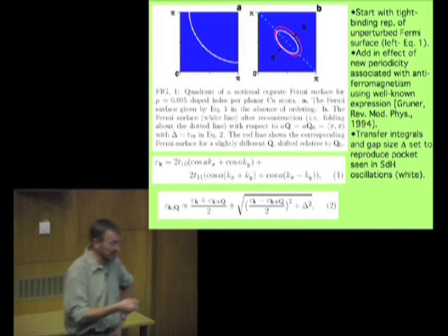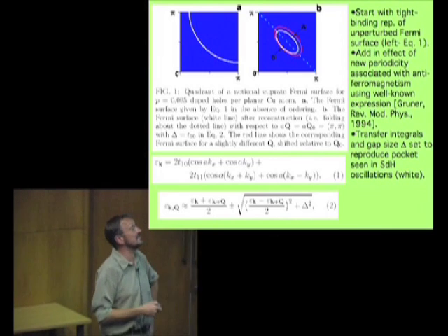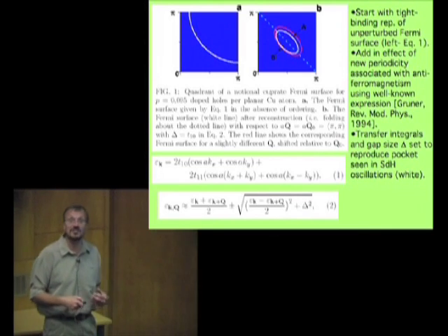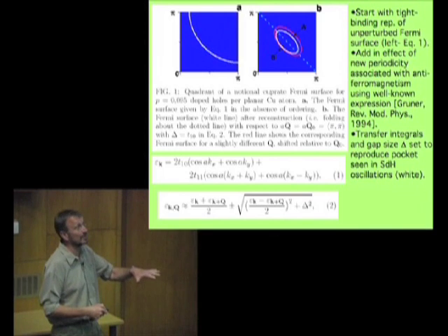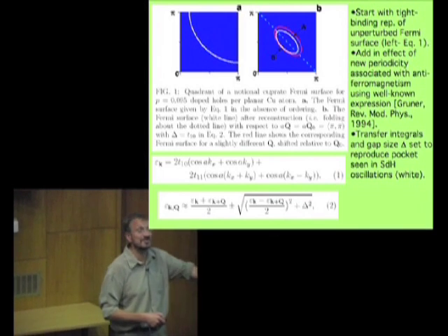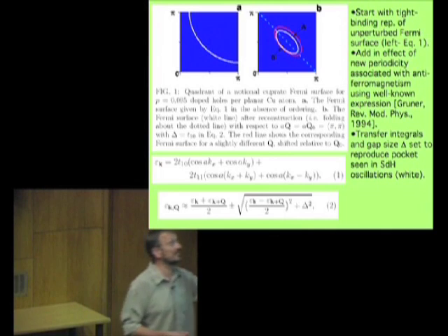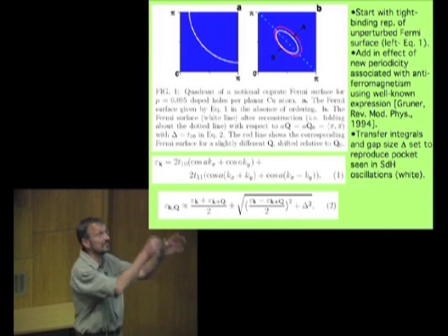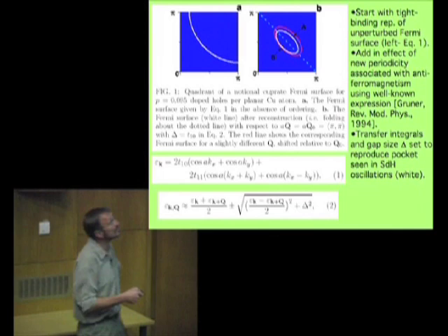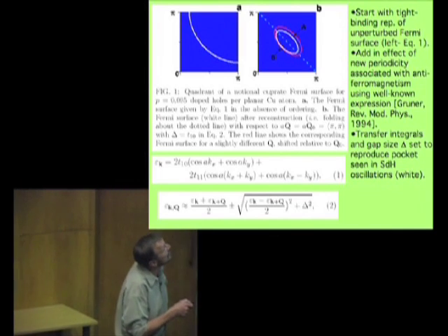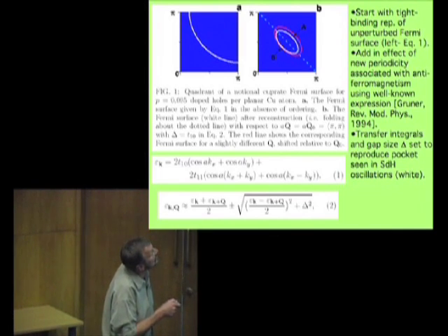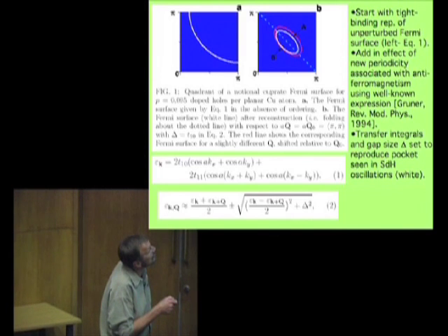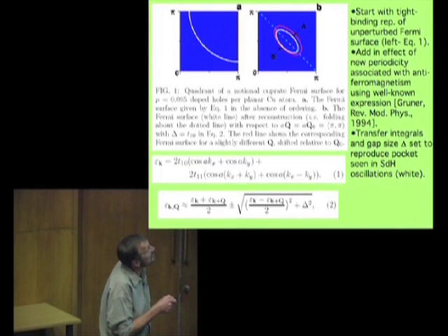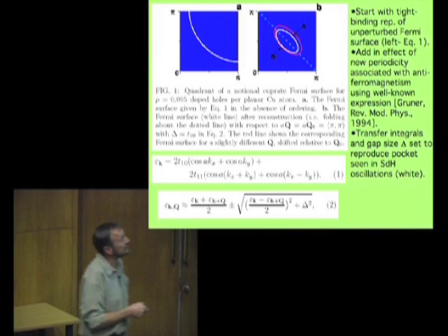Now the neutron scattering measurements show that this fluctuating antiferromagnetism has a very short correlation length. That means that if you measure it in one place, it has a different periodicity than in another place. If you measure it in a third place, it has a different periodicity still. There's a kind of distribution of these periodicities. So what effect would that have? Well, if we have a slightly different periodicity, a smaller periodicity in real space corresponds to a larger distance in K space, so it means pushing this boundary out slightly. We then end up with this red pocket here.